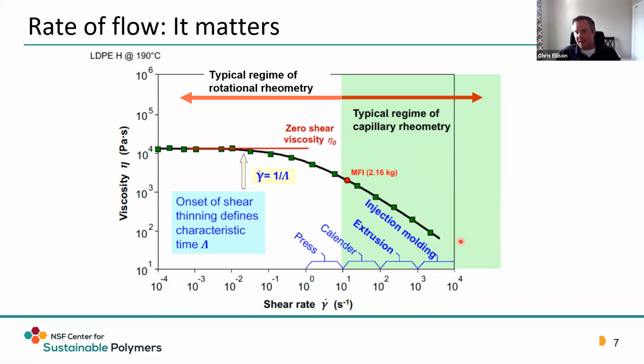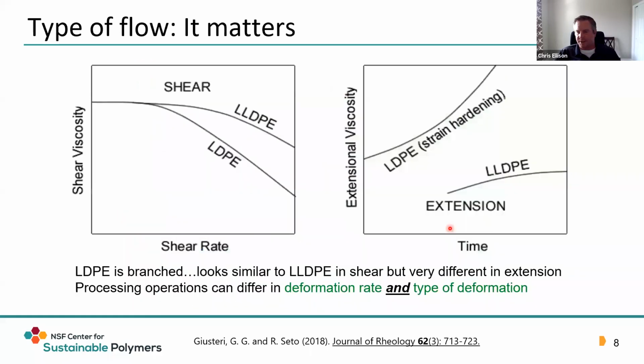This means that a given material may adopt several different viscosities in several different types of processes. I'd just like to point out that measuring the rheology or viscosity of these systems over such a wide shear rate range typically requires using several different types of rheometers: rotational rheometry at low shear rates, and capillary rheometry at high shear rates.